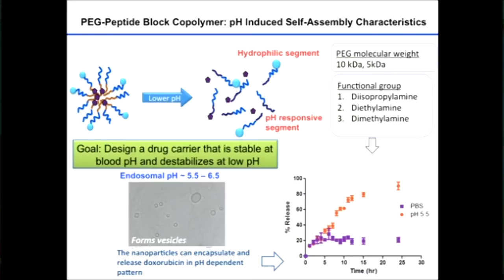So we can encapsulate something like doxorubicin, which is actually a hydrophilic drug, in the interior of these vesicles, and then we can look at their rate of release and find that in PBS they release very little. However, when they are in this pH 5.5, which is close to the endosomal pH, we can see a very, very nice and complete release over a time period of within a day.